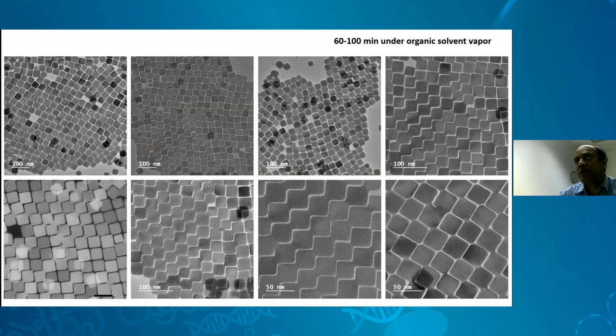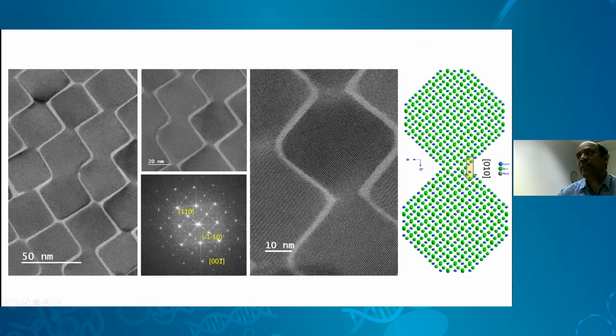Wherever the self-assembly is available, it has been connected. This indicates that the connection happens on its own, which is a step forward in making devices without making defects in the intermediate. You could see in the HRTEM images that there is no defect when they are connected. They are simply single crystalline and connected, and still remain with a space in between the two lines. Again, if you see the atomic models, it is clear that the connection is as per the new facets, or the directions in which it has been formed.